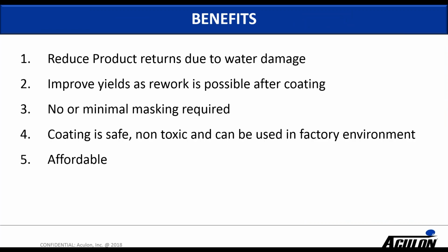So to get into the key benefits of these products. They can reduce product returns due to water damage. These products are also reworkable. It's very simple to rework them with a little bit of diluent solvent. The coating can be removed, the part can be reworked, recoated without going into a deposition chamber, and then those parts don't need to be scrapped. Huge benefit, something that everyone is looking to get away from, is no or minimal masking is required. In almost all cases, these can be selectively applied, and so the masking and demasking process is fully eliminated, and that's just a huge labor and time saver. These coatings are safe, they're non-toxic, and they can be used in a factory environment, and they're certainly very affordable relative to the other options that are out there.